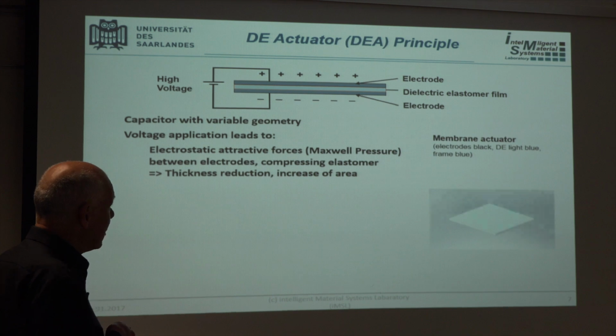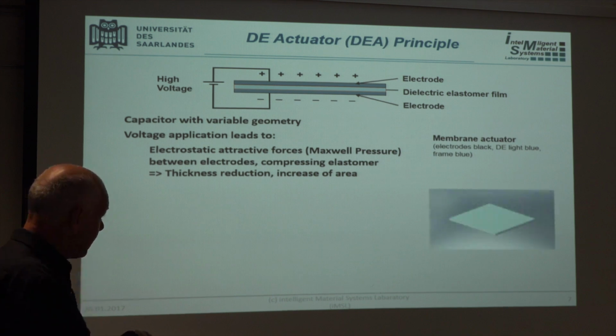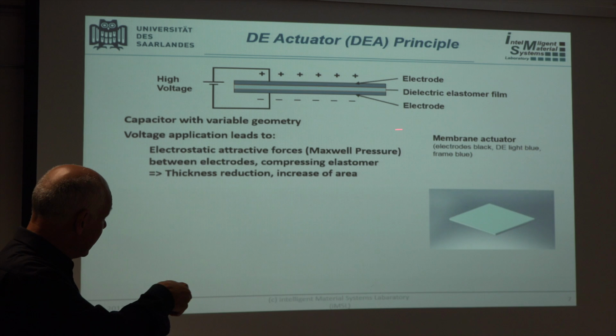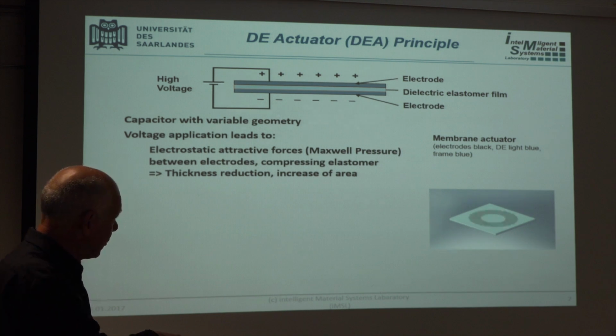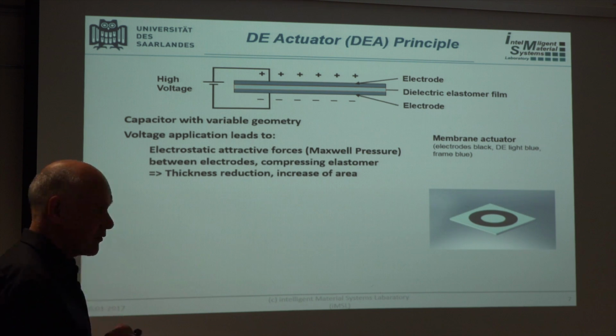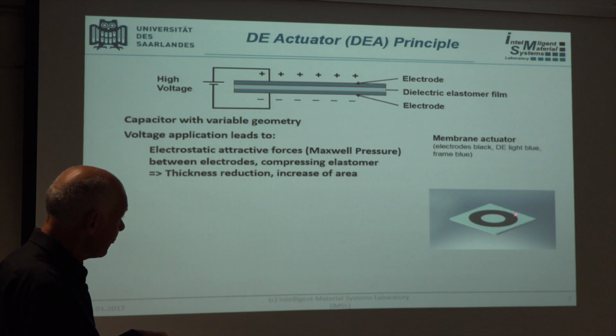So how do we build actuators with them? One example is here. This is the dielectric elastomer film. We print electrodes onto the film. These electrodes are typically made with a mixture of carbon black and PDMS silicone. The film itself, I should have mentioned that, is also silicone that we use.